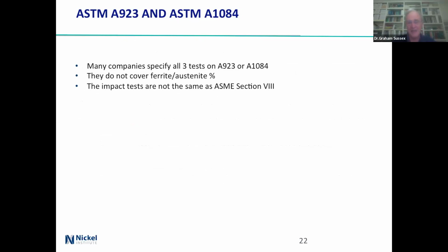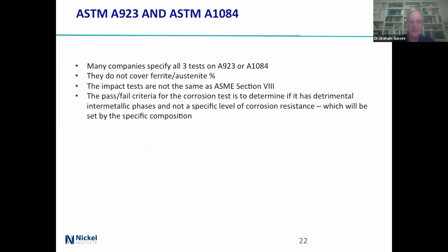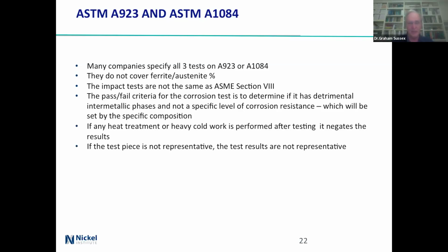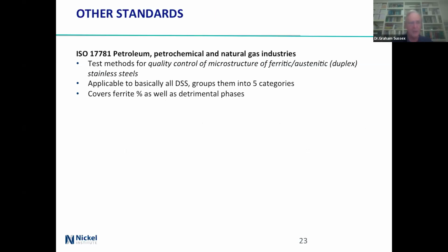And the impact tests aren't the same as in ASME 8. The pass-fail criteria for the corrosion tests are to look for detrimental phases, and it's not looking for a specific corrosion resistance, which may be set by the specific composition. So you may get away with having a certain amount of detrimental phases, and that rule may say no, but if you actually do a test, it may well be okay. If you do any heat treatment or heavy cold work afterwards, it negates the results completely. And where's the test piece from? Is it from the thickest bit or the thinnest bit, or is it near a weld? If it's in a place that's going to fail, then yeah, you need to be in the right place.